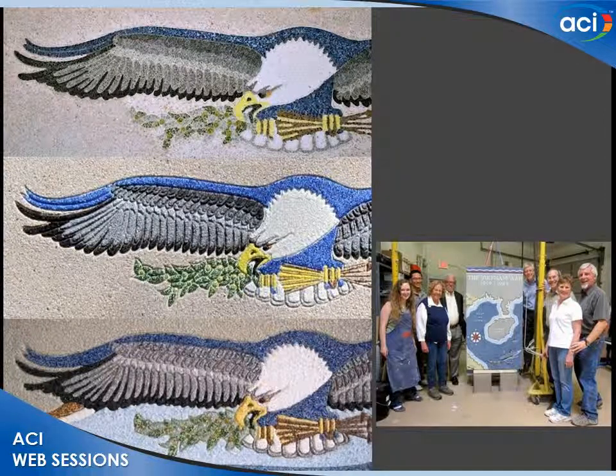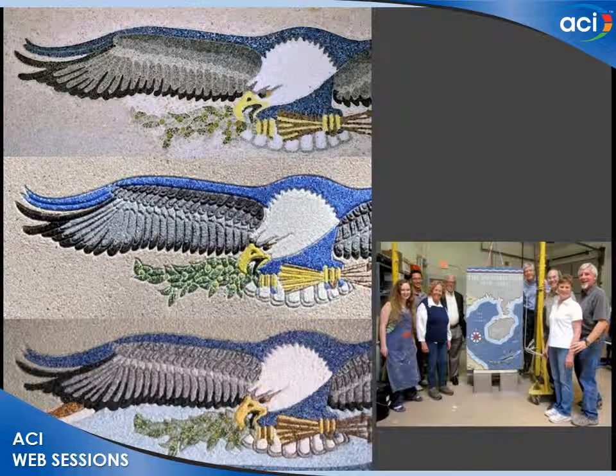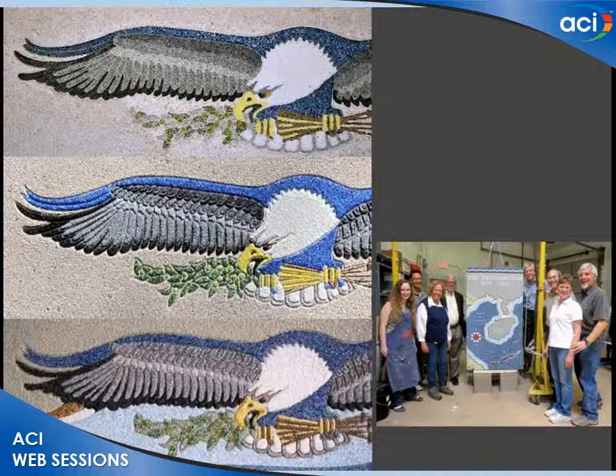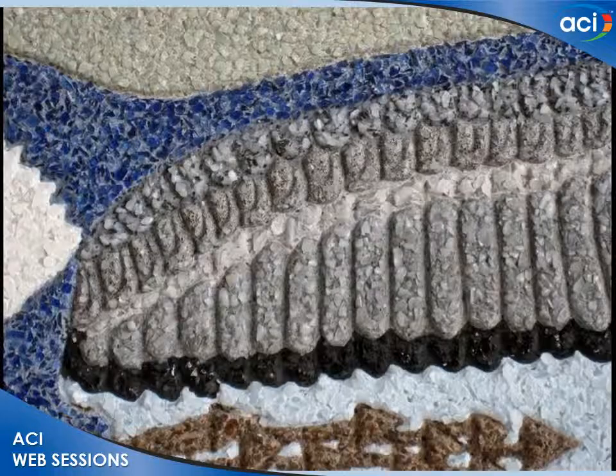The middle photo shows the first test sample we made. And, of course, the colors were too bright. Everybody realized that, but everything else worked pretty well. So then we went through adjusting our colors and the whole process, and the bottom shows the final panel with the eagle up on the Vietnam Memorial. And in the lower left, you can see when some of the commission staff and the architect and Mary came out to our studio to look at what was actually the first mock-up, but it turned out so well that we were able to use it in the project, so that was nice.